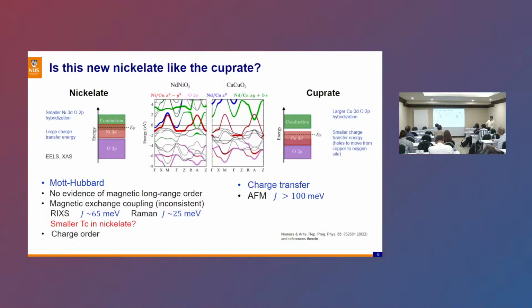And then there are many other experiments that I'm not going to talk about today, but just to highlight. For example, from the EELS and X-ray absorption spectroscopy, it's consistent with having less hybridization between the oxygen 2p and nickel 3d in comparison to the strong hybridization that we have in the case of cuprate. So this also leads to the idea that in the case of nickelate, from the framework of Zaanen, Sawatzky, Allen, we have this Mott-Hubbard framework rather than the charge transfer as in the cuprate.